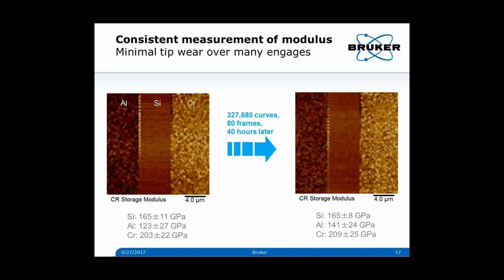Okay, so here's an example using diamond tips. We get extremely consistent measurements. This is 300,000 curves and 80 engages later. Looking at this sample with aluminum and chromium films on a silicon substrate, we just get a tiny increase in aluminum and chromium moduli, but the measurement is very, very stable.